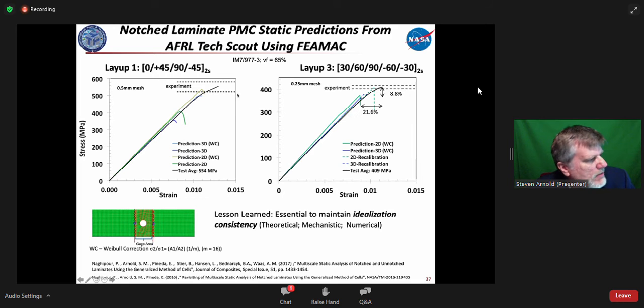Again, kind of the point of showing this slide is we're showing here 2D shell predictions as well as the 3D, which are in blue. And what was interesting to us is the fact that we characterized our parameters using MAC and lamination theory, and so it was interesting that the 2D shell was much more accurate than the 3D. And that just ties in with this idea of idealization, consistency, and the need for that.